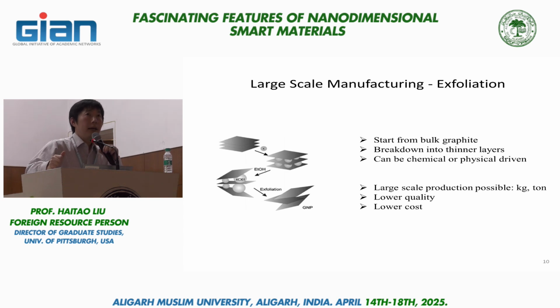Phosphorus being another one. Those materials, because of their layered structure, can be expanded by inserting something between the layers. Okay? And then you can imagine that insertion would weaken the van der Waals interaction between the layers. And then you can do something else to force the layers to come apart. And so that's the exfoliation. Now later people found it's actually not necessarily required to have this insertion process. Okay? So in this particular case, what people did was to insert alkali metal, potassium or lithium, and then put in water, and the production of hydrogen and other gas will expand the sheets of graphite into graphene pieces.